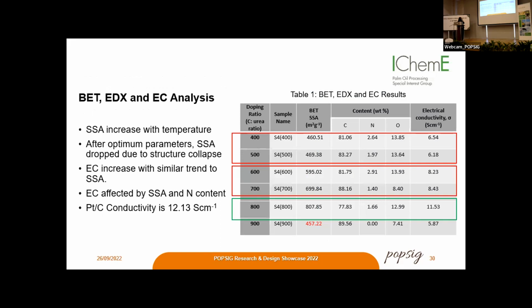Last but not least is the BET, EDS, and EC analysis, which is the electrical conductivity. So through observation, the specific surface area increases with impregnation time, carbonization temperature, carbonization time, and activating agent dosage. After the optimum parameters, the specific surface area tends to drop due to the collapse in particle, porous and carbon structure. Another finding is that the electrical conductivity increases with a similar trend to the specific surface area.